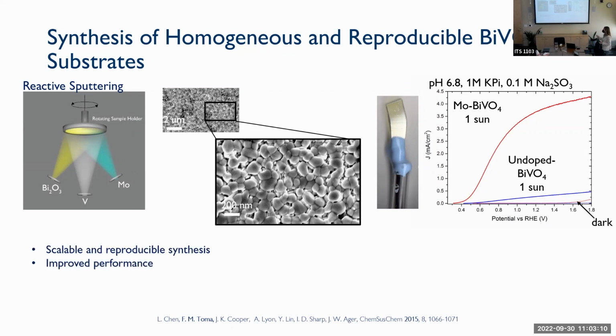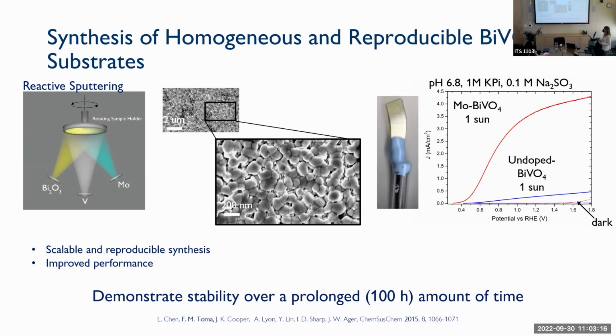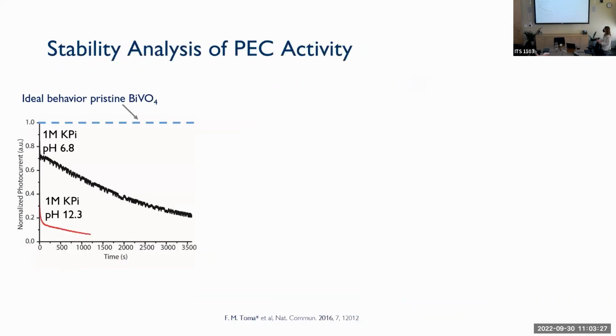So we show that we can make this material scalable and reproducible. We show that we could improve the performance of the material. And then the next step for us to demonstrate that we could actually make a working device was to show that the material had a stability of at least 100 hours. And this is when I became very sad.